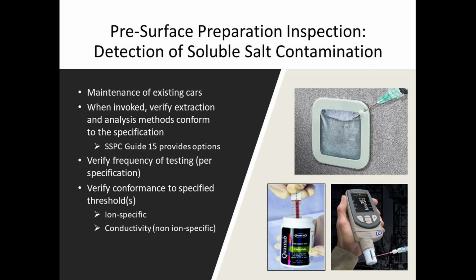What some people are looking at doing is they're not being ion specific. They're just simply extracting a sample from the surface using distilled water and immediately depositing it onto a conductivity meter because they really don't care what salt it is. If it's at a high enough level, they know they're going to have to do some pressure washing or water jetting to reduce that surface concentration down. It doesn't really matter whether it's sulfates or chlorides or what the salt is. So we can do non-ion specific testing or we can do ion specific testing if we really want to know what the bad actor is.